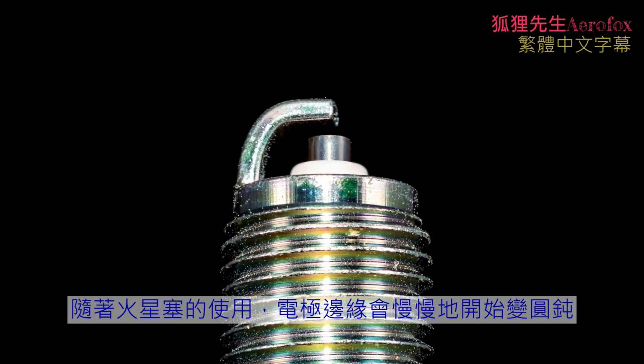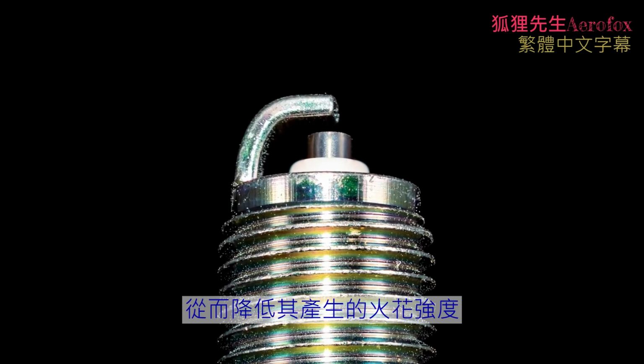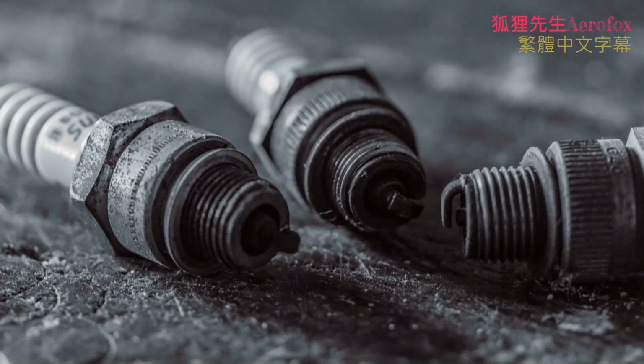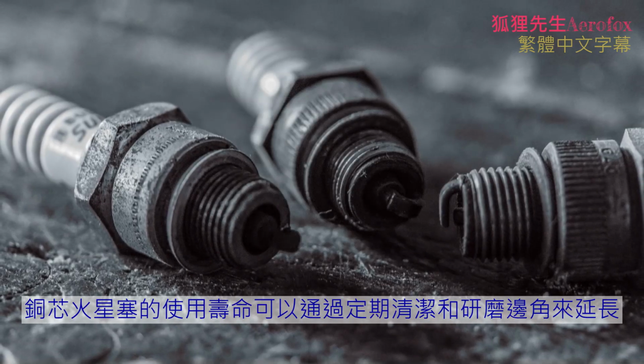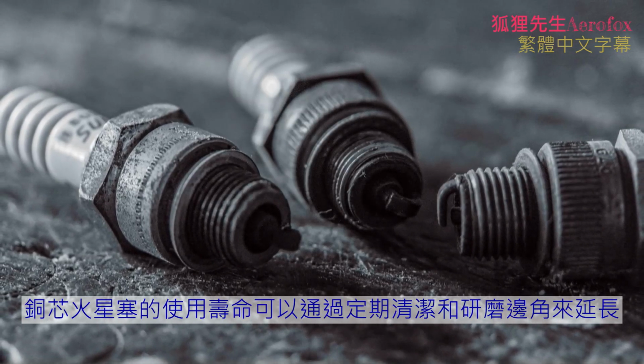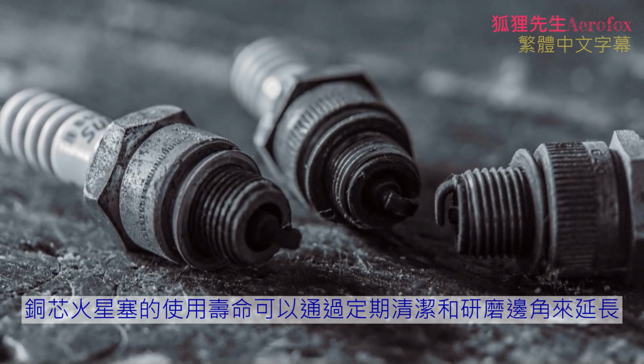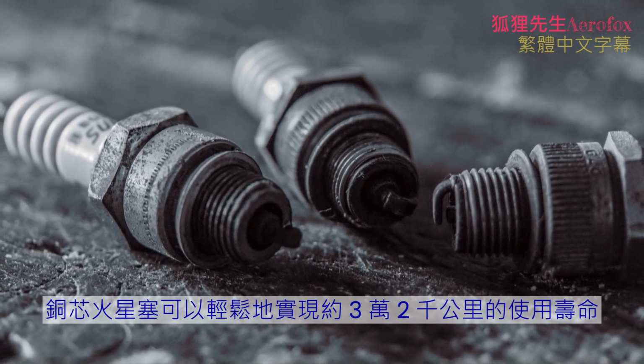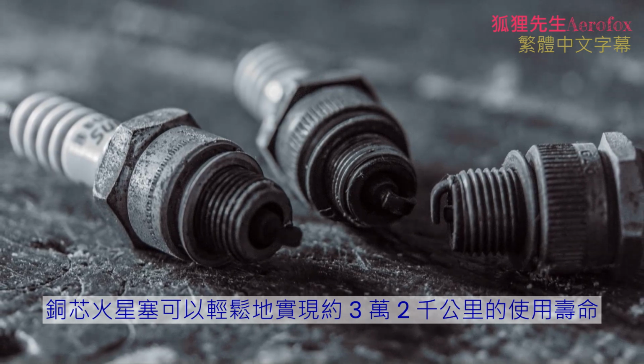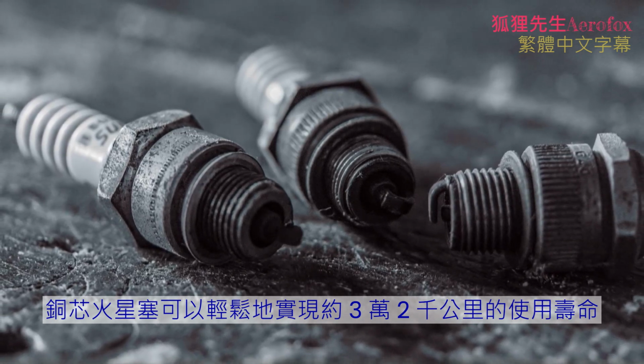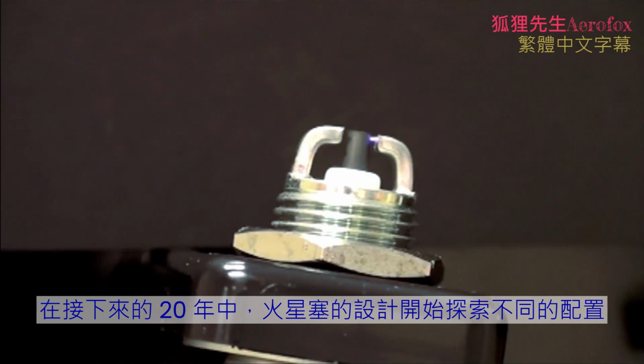As the plug wears, the edge will slowly begin to round over, reducing the strength of the spark it produces. The service life of a copper core spark plug can be extended by periodically cleaning and refiling the end back to a sharp edge. Copper core spark plugs can easily achieve a service life of around 32,000 kilometers or about 20,000 miles. Over the next 20 years, other configurations of spark plug designs would be explored.